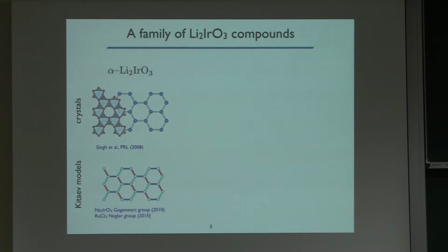So the material is layered honeycombs. And on the left-hand side, I indicated how the oxygens are placed, and you see you have a really perfect edge-sharing octahedral structure. And people were very interested in this because this gives us the first material that really realizes a Kitaev-like Hamiltonian on the honeycomb lattice. And in fact, you don't have just lithium iridate, but you also have sodium iridate and ruthenium trichloride. So there's a lot of experimental study going on for these three materials.